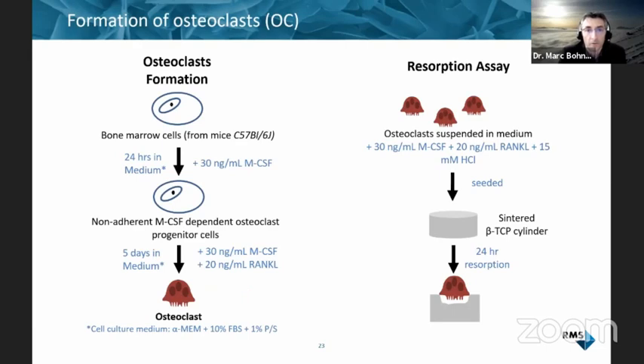The production of the osteoclasts is given here. We started from bone marrow cells. This is work done at University of Bern. The non-adherent M-CSF dependent osteoclast progenitor cells were then cultured with M-CSF and RANKL, and then the osteoclasts were suspended and seeded on the material. We had a TRAP staining to identify that they were TRAP positive cells. We had an ICP-MS analysis of the cell culture medium to look at calcium and phosphate levels, and strontium and copper if we had doping. And then we cleaned the surface and looked at the resorption.